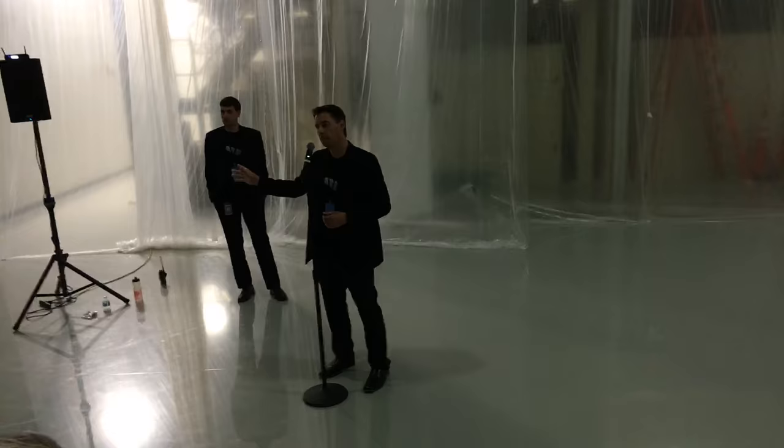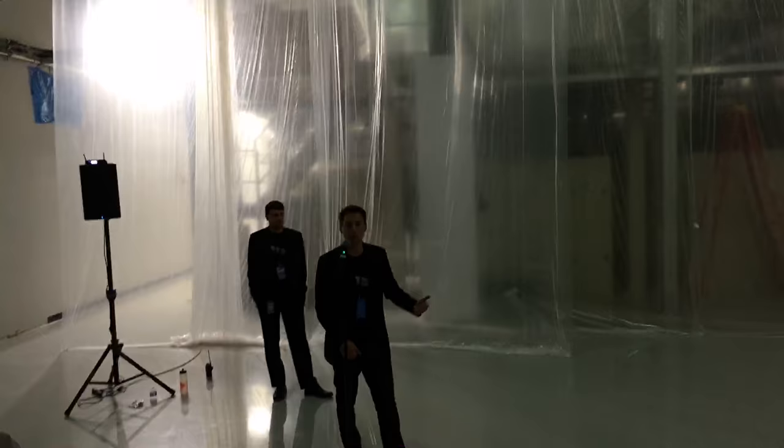And we then pump that slurry all the way down to the far end of this room on the ground floor. The very end down there, we have a coating booth, where similar to a printing press, we take that liquid slurry and apply it to a very thin piece of metal substrate that is being unrolled on this very large roll. This wet slurry on top of the substrate is then passed towards us inside the first row of